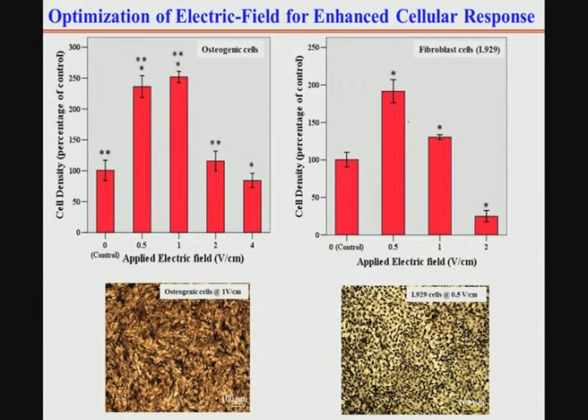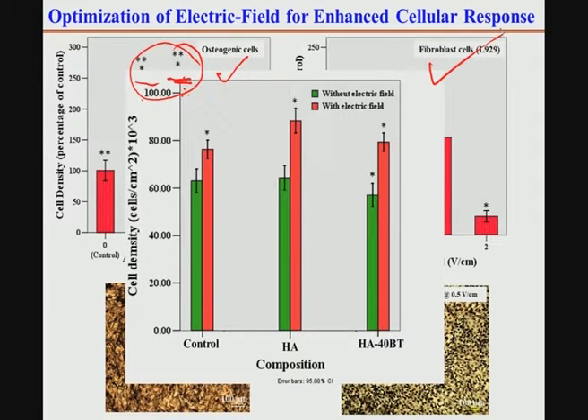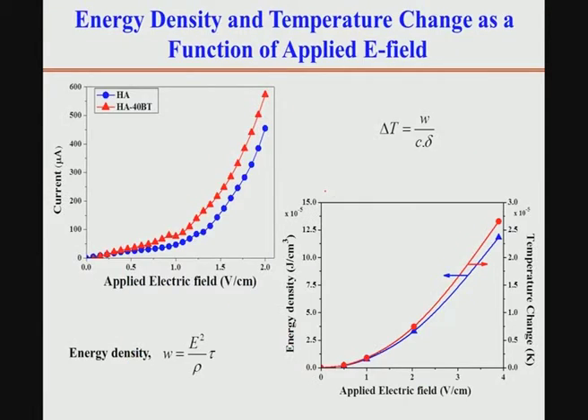Now, when these cells are cultured at different field strength conditions, like 0.5 and 1 volt per centimeter, you can see that at 0.5 and 1 volt per centimeter it shows a statistically significantly higher number of cells. So, essentially it shows that cell growth goes to a maximum at a very narrow window of 0.5 to 1 volt, both for osteogenic cells and fibroblast cells, that is the L929 cells. And when it is grown without electric field and with electric field, it also shows that hydroxy barium titanate has higher cell density with respect to unstimulated cells, which do not receive any electrical stimulation.